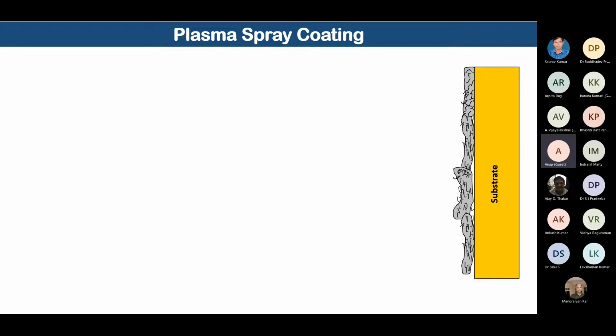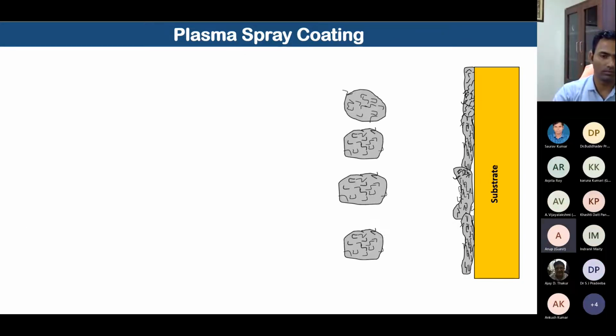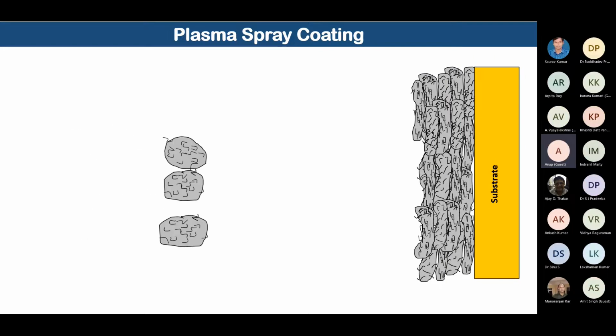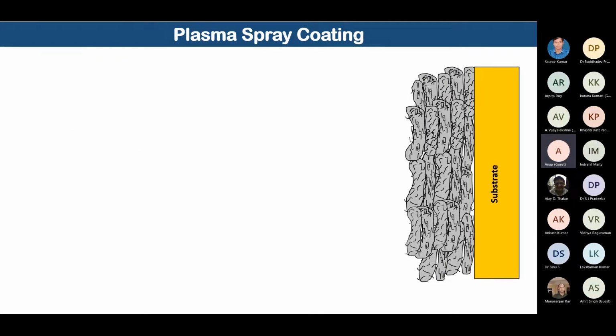So you can see that this process is called layer by layer deposition. Layer 1 has been deposited, and now multiple layers keep on depositing. These individual layers are called splats, a single splat, and the multiple layer by layer deposition is known as your coating. The thickness of this coating depends completely upon the application, whether we want to use this coating for a corrosive environment, for oxidation, or for tribological properties, right? Based upon that, we keep on manipulating the coating thickness. But I hope you are now able to correlate what plasma spray coatings are.